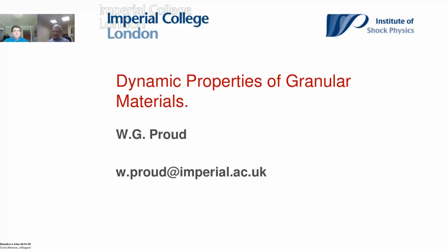Concerning that, we tried to use our fundamental results from the study of fragmentation. It was an in situ experiment where we studied dynamic loading of ceramic materials and also glass, by dynamic loading and fracture luminescence framing, in recovery conditions, because we were very interested in the statistical distribution of both fragments and time between peaks in fracture luminescence signals.